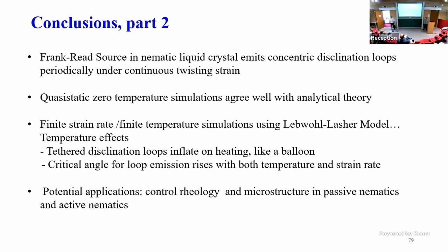So you're making a nice connection between the line defects and active matter. But what about using that control over the line defects in liquid crystal elastomers? That gives you, I'm sure, yet another whole space of control. Okay, so this could be done with the material before it's cross-linked. Once it's cross-linked, the defects are localized in the microstructure. You could, in particular, put a source in the middle of a sample, spin this thing around a few times, and just get some concentric rings and then cross-link that. However, we have other ways to control the microstructure just by putting a static anchoring pattern on the top and bottom. On the other hand, you never know. We might be able to make something dynamically that you can't make statically. I don't know. I have to think about it, though. It's an interesting idea.